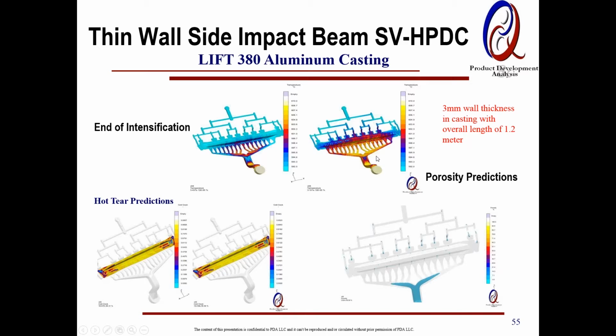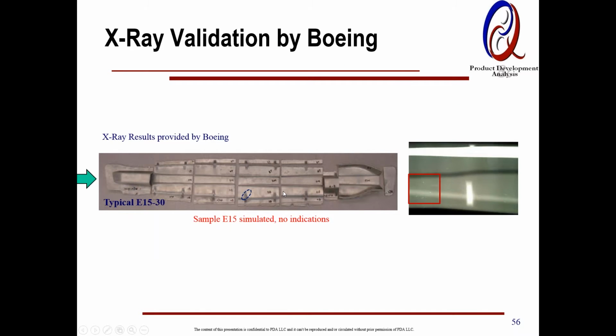This is actually a quick repeat just to demonstrate the point that ICME is so valuable. And this is part of the MELT 51B project on thin wall aluminum that was spearheaded, managed by Boeing, where we were able to predict the porosities and the hot tears. We ran a bunch of casting. It's a 3 millimeter wall thickness. And we were able to find a very good correlation to what the X-ray results showed us.